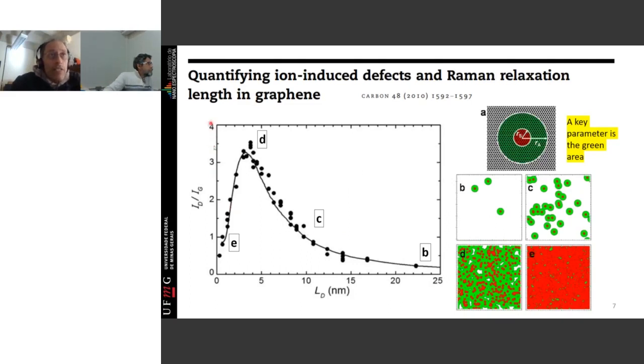And then you can make one interesting picture, that is, take those two Raman peaks. This is the defect peak, and this is the usual graphite peak or graphene peak. Take the ratio as you increase the amount of defects, or decrease the LD. LD is the distance between defects, okay? The average distance among defects. And what you see is that as you decrease the distance among defects, the defect peak will increase, but then it reaches a maximum and it decreases.